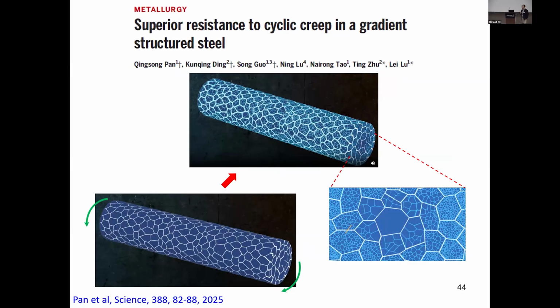So based on those understanding, recently we further pushed the limits of mechanical properties of structural materials to the long-term stability, not only for this strength and ductility combinations. In this case, actually, we refine the microstructure through this cyclic torsion. So we apply the cyclic torsion to introduce this gradient dislocation cell structure within the grains.